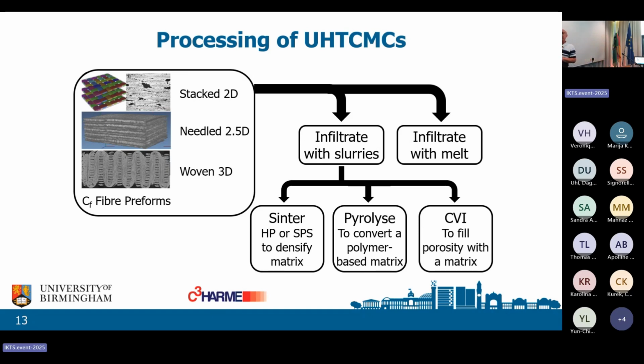So you can move to needled 2.5D. This is where you stack them, but then you send a needle down with a fish hook on the end, and it pulls one fiber from one layer to the layer above. It gives you a small amount of reinforcement in the Z direction. Or you can go to woven 3D. The whole thing is a woven structure. As you would imagine, cost increases as you come down. Performance increases, and so does cost. Cost is not linear, not by any means. So woven is much more expensive than the needled, and needled is more expensive than the 2D.